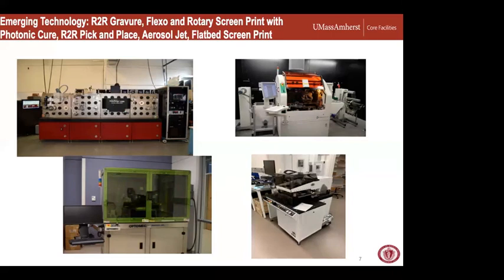Top right is the Besi Evo 2200. That is an automated pick and place tool. This is kind of an industry standard tool that's used within the semiconductor and packaging industry. We have adapted that to be roll fed, so you can have a pre-patterned substrate unwind. It indexes about 12 inches at a time, and then the tool itself will populate that with either surface mount components or silicon devices. It gets pretty good feature resolution, I believe, plus or minus 7 microns. So you can come in with some pretty sophisticated silicon chips and align and assemble them onto your substrate with good reliability.